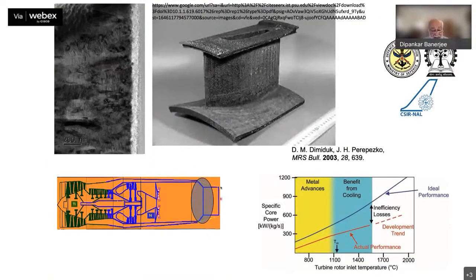If you want to migrate these composites into the turbine section, and there are very good reasons for doing so. You want to migrate these composites into turbine sections because these materials have a higher temperature capability than nickel-based superalloys, and they're lighter than nickel-based superalloys. And because they have a higher temperature capability, they need not be cooled. And if they do not require cooling, then you don't have to extract work out of the compressor to drive cooling air, and therefore you improve engine efficiencies.